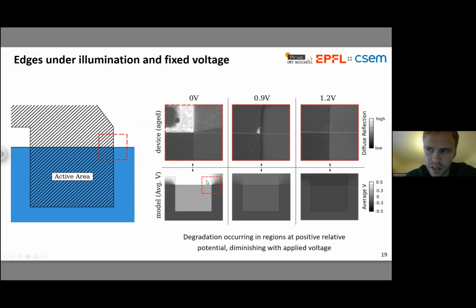And this is quite interesting because there have been a number of studies on lateral devices, so not solar cells, but these sort of interdigitated contact devices where you typically apply kind of a large bias voltage between fingers on top of your perovskite or buried beneath it. And usually whenever the degradation is seen there, it's happening at the anode, so at the region at positive potential. So it seems to be consistent with that finding.